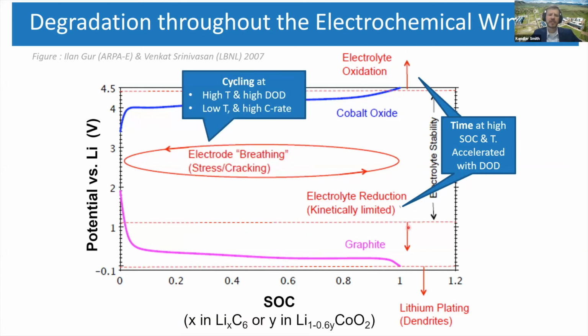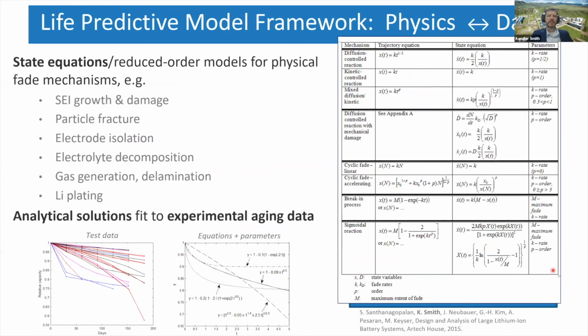Some other observations are you can track the electrode damage versus number of cycles. That definitely accelerates at low temperatures where you have diffusion-induced stress, especially at high C rates. We also see some damage occur that looks analogous to this at high temperatures and high depths of discharge. This is something I'm not exactly sure what the driving mechanism is. And then finally, if you do fast charging, you can certainly exacerbate other side reactions such as lithium plating and cause loss of lithium. And so what we've come up with is a framework of reduced order models.